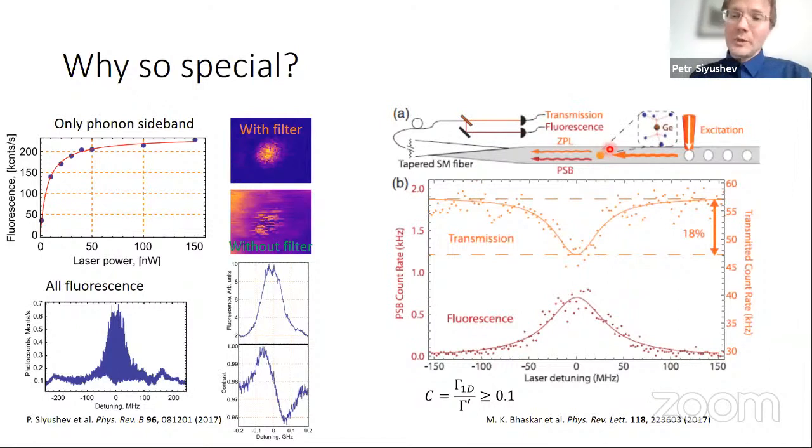And also, please note that in this configuration, the defect is placed really close to the surface. And as I said, for nitrogen-vacancy center, you always have instability of spectral lines because of the strong Stark shift, especially if it's placed close to the diamond surface, as here. And here we can see the line pretty easily and nicely without any specific treatment.